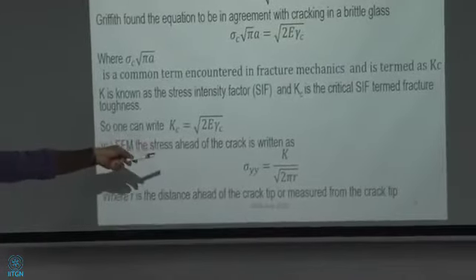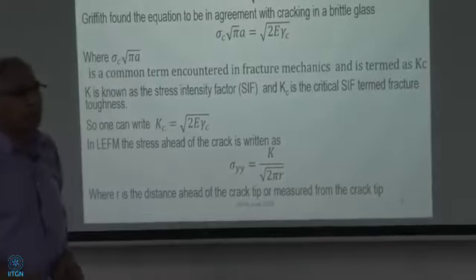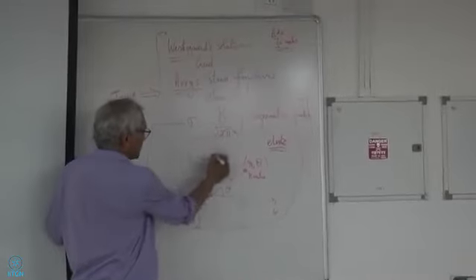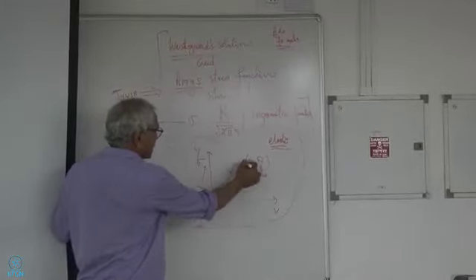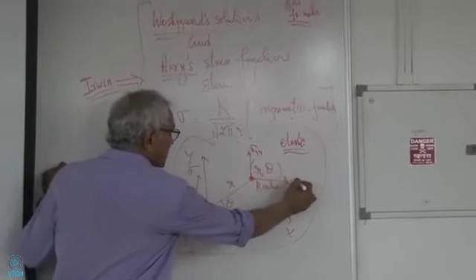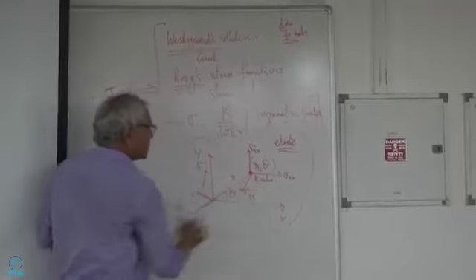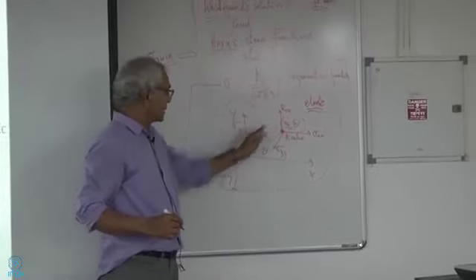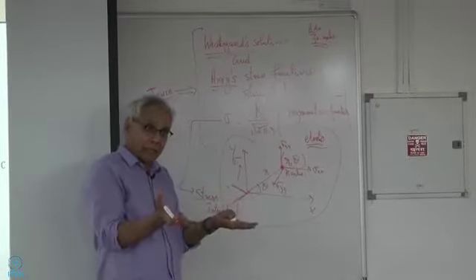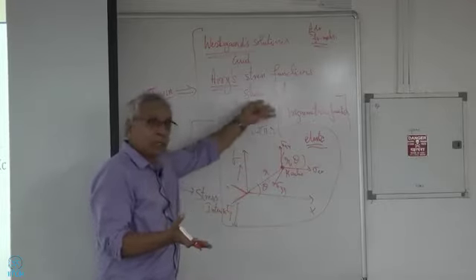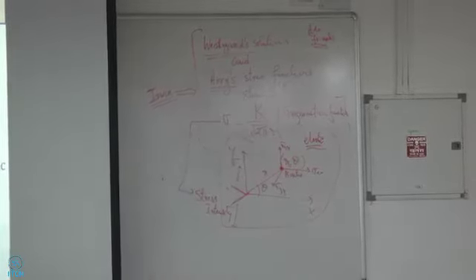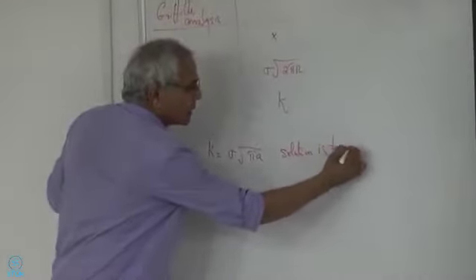So in linear elastic fracture mechanics, the stress ahead of the crack tip is written as sigma YY is equal to K divided by square root of 2 pi R. And this is your sigma YY. This is your Y direction. So if you take this point here, sigma YY, sigma XX, sigma ZZ, you can define all the three stresses at any distance R from a crack tip in an elastic body. This solution, however, was for an infinite plate. I didn't write it down there.